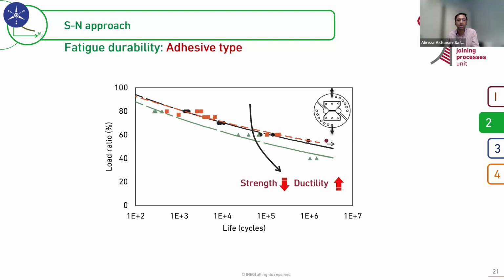In case we are talking about fatigue crack growth, probably then we might have large deformations. So in that case, the propagation is not controlled by stress itself, but by energy, which is a combination of stress and strain. And strain at failure can be an important parameter. So again, I cannot make a general conclusion, but stress, maximum tensile strength for more brittle ones and for SN-based approaches, and for more ductile ones and for fatigue crack growth, probably the maximum elongation at failure. Yeah, this makes sense, I think.